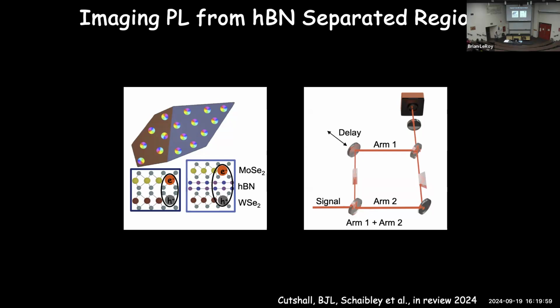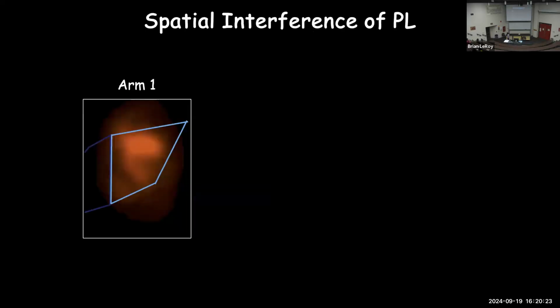And I'm going to take the two images and rotate them 180 degrees. So I'm going to interfere this position of the sample with this position of the sample. If they are a uniform macroscopic state here, then I should be able to interfere those two positions. If there's no correlation, then it'll just be like two separate photons, and I'll get nothing interesting in the interference.